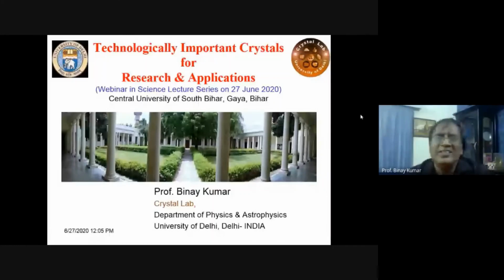What does it mean? The Czochralski method is known for growing crystals whose melting point is above 800, 900 up to 2000, because we use a very good quality furnace, induction furnace or resistive furnace. So we require a very specific type of temperature gradient at the melt and solid interface. This technique has never been used, and no one has thought of using it to grow organic crystals whose melting point is 50 degrees Celsius or 120 degrees Celsius.